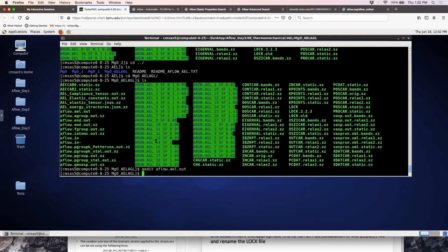we can get as a function of pressure pretty easily, because you can get the pressure-volume curve from AGL. Then you work backwards to work out what volume corresponds to a particular pressure, and then you can calculate the elastic constants at that pressure. This is something we can do with AFLOW. It's already implemented.